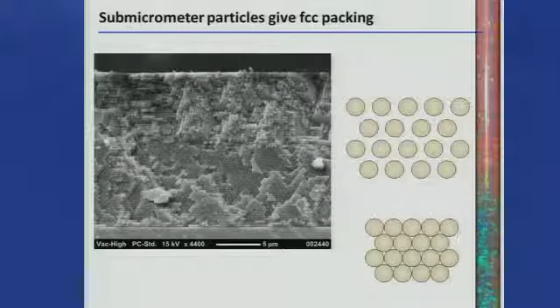So you're famous in the chromatography world, as well as the spectroscopy world. And so this is a picture I showed Sandy last year at Pittcon, where my student Robert Birdsall took a Pasteur pipette. So this is a big blow up of it. And he let it sit for a month with a concentrated slurry of silica particles in them. And silica at neutral pH has a charged surface. And so when these get really concentrated, they form a Sandy Asher type of colloidal crystal at the top, which has bigger spacing, so you have red diffraction. And then as they drop and form the solid, now they're closer together and you get this green diffraction.